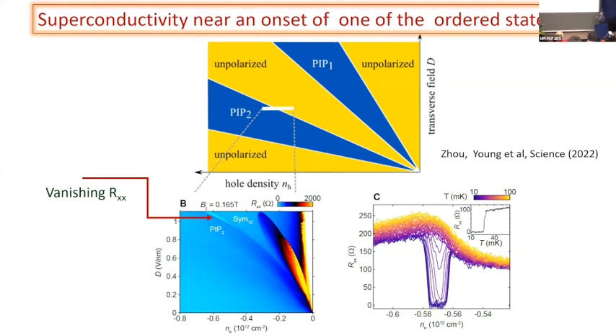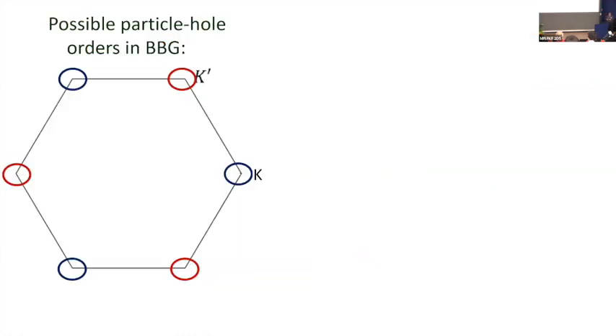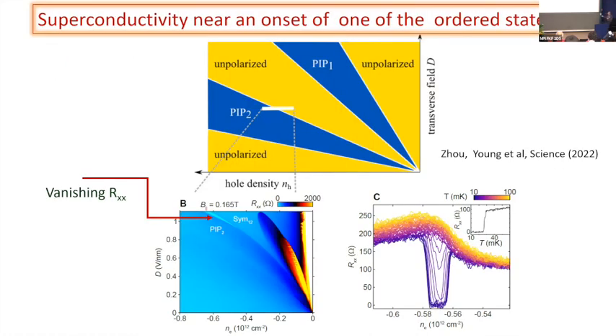Besides everything else, let's talk about superconductivity. There is superconductivity near one of these orders — let's not specify which order at this moment. It's not as spectacular in the displacement field versus density plot, but if you look at lower temperatures, you see that resistivity goes down below a particular temperature: it's about 30 millikelvin. So superconductivity emerges when the system is about to become ordered.